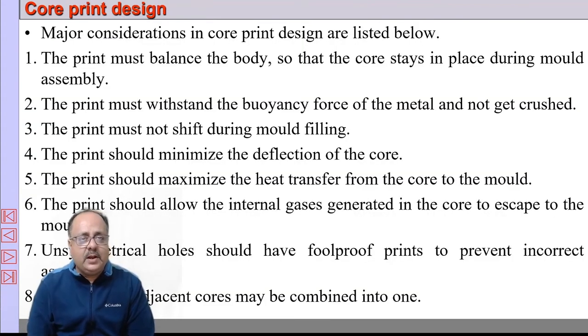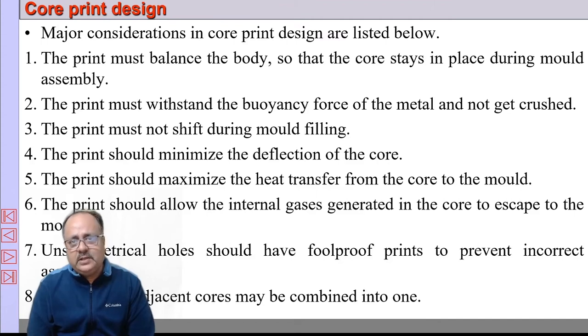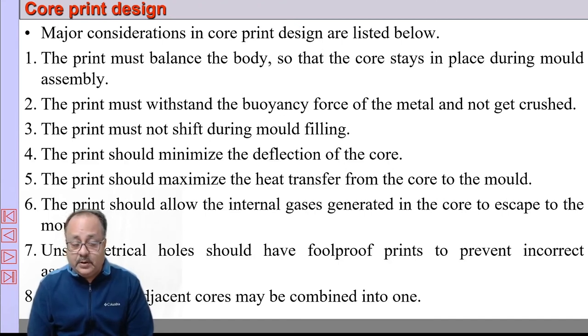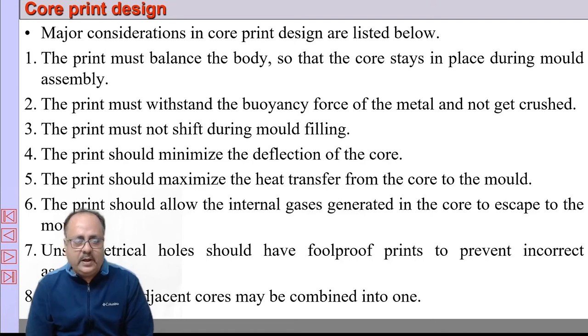An important design aspect is core print design. The core print must balance the core body so that it stays in place during mold assembly. The print must also withstand the buoyancy force, must not shift during mold filling, must not deflect, and should help in heat transfer and allow gases to pass. An unsymmetrical hole should have foolproof prints to prevent incorrect assembly, and the prints of adjacent cores must combine into one.